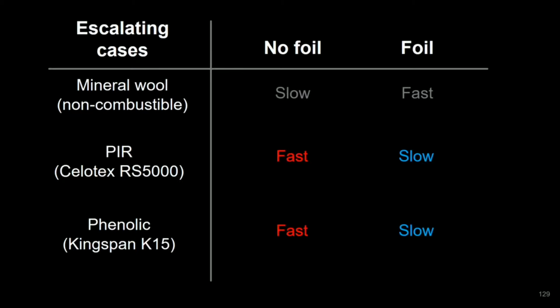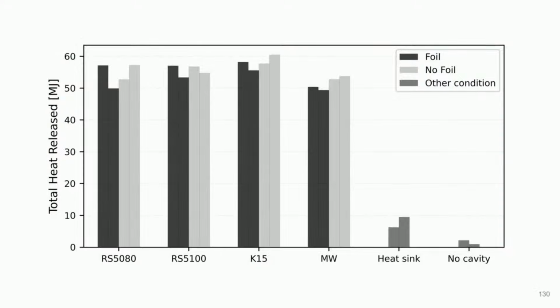I consider this to be a useful summary slide in some respects that gives an overview of the differences between the various configurations that I've investigated in my Phase 2 Work Package 2 experiments. This plot shows the total amount of energy released during different experiments on different combinations of products, so each bar represents a different experiment, with each experiment performed twice, which is why you have 2 of each bar. We ran every test in duplicate because we wanted to check the repeatability of our results.